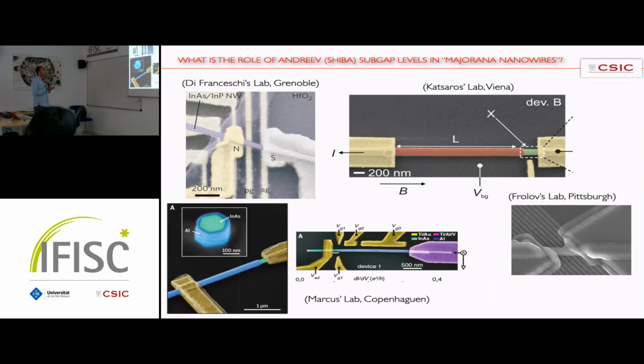Here, this is one of these new generation of devices called full shell nanowires. This is a semiconducting core, the green part, the indium arsenide core, which is epitaxially covered by a very thin layer of a superconductor, in this particular case, aluminum. And again, you see in the image how you have the blue superconducting shell, but there is some uncovered part, which is the one that you use as a tunneling region, all right? And the point I want to make is that in many of these cases, because you want to create a tunneling region, unintentionally, you create quantum dots. And you actually have to consider the physics of quantum dots in this kind of systems.